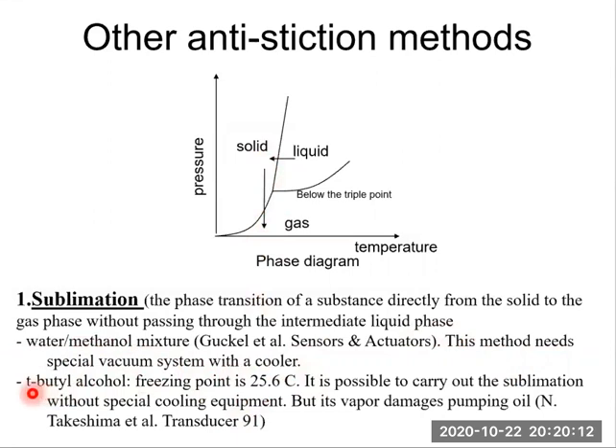People have also used T-butyl alcohol, whose freezing point is 25.6 Celsius. So at room temperature, for example 20 Celsius, T-butyl alcohol is a solid. So we can do sublimation using just a conventional vacuum system without a cooler. We don't need a cooler because its freezing point is pretty high, 25.6 Celsius.